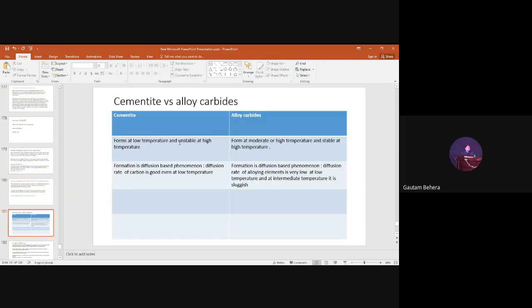Now, for that, I have this one: cementite versus alloy carbide. You can easily write that cementite is stable at low temperature, but alloy carbides are stable at very high temperature in steels. Stable means they will not dissolve. So cementite will dissolve if you take the steel to 750 degrees centigrade, or above 650 it starts dissolving in the austenite matrix, right? But alloy carbides can go up to 1250 degrees centigrade, 1300 degrees centigrade, like that.